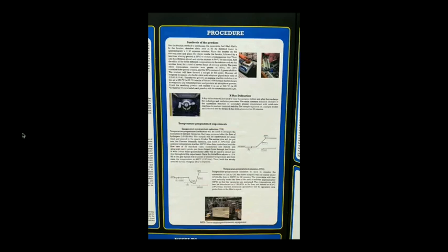In the TPO experimentation, I did the same thing, except this time I let the sample cool until it hit 500 degrees Celsius, and then I flowed helium and carbon dioxide gas through the tube. And this carbon dioxide gas mimics the carbon dioxide that it would be taking in from the environment.